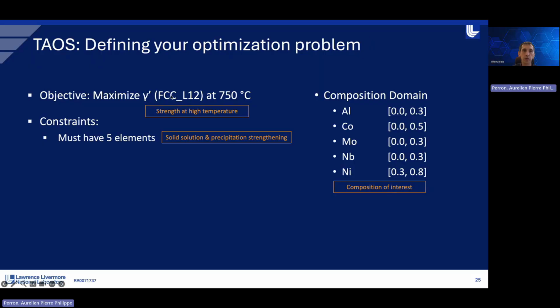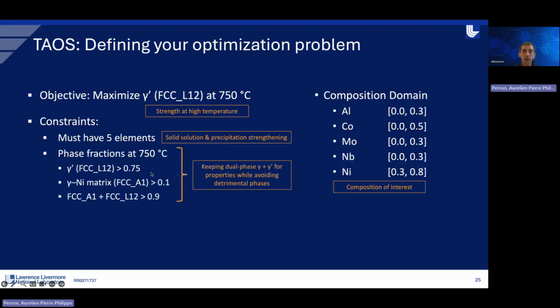Then you can add some constraints. You say, okay, I want my alloy to have at least 5 elements, because ideally I would like to combine solid solution and precipitation strengthening. So you can do that. Then your service temperature is 750. Of course, you want to have a lot of gamma prime. That's our target, but we want at least 75% phase fraction of this phase. That's a constraint during our optimization. We also want to keep at least 10% of the initial FCC nickel phase. And overall, we want the summation of these two phases, the nickel initial matrix phase and the precipitates, to be above 90%. Why we do that is to try to minimize the amount of detrimental phases or other phases that could form that you want to avoid.